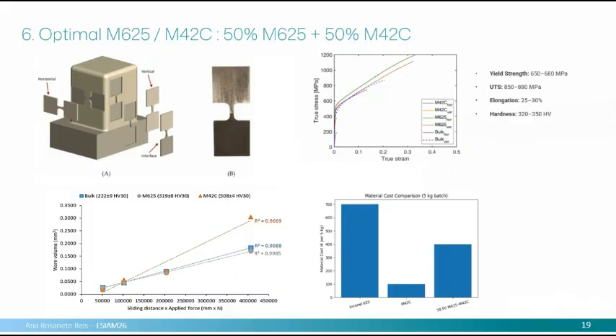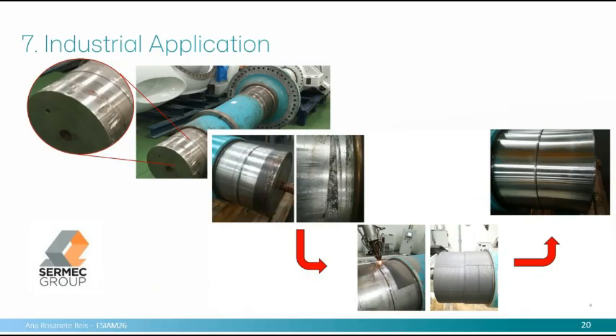This is not very interesting, but at the same time, for the company that we were working with, it was quite an interesting solution because of the price of the materials. The Metco is a water-atomized powder, so it's very cheap. The idea is that you could replace 50% of the Inconel with this and get the same properties, because we see here we get a little bit less ductility, but we could still have good properties. So this is what the company chose.